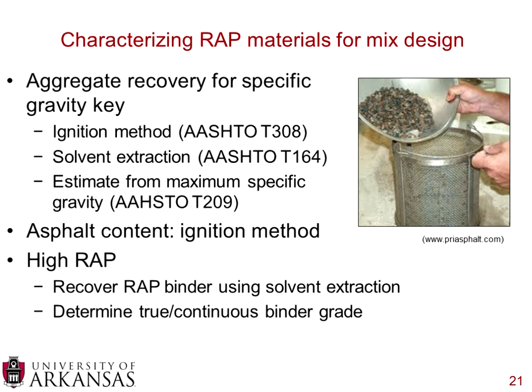The first is the ignition method, and that's AASHTO T308, where you place the sample in an ignition oven. It's heated up very, very hot, and the asphalt cement is burned off, and you're able to then take the aggregate out of the oven and run your specific gravity. You can also run a solvent extraction, which is AASHTO T164. This is where the chemicals pull the asphalt off of the aggregate and you're left with your aggregate sample. And then there's a third, AASHTO T209, where you can estimate the specific gravity from the maximum specific gravity of the RAP sample. So there's three different ways to get your specific gravity.